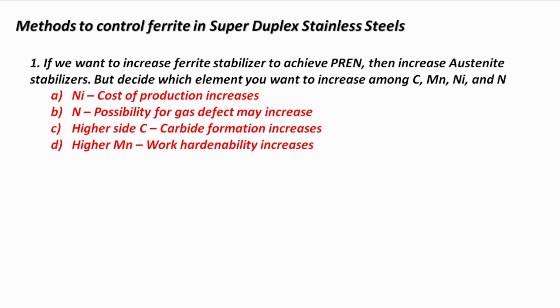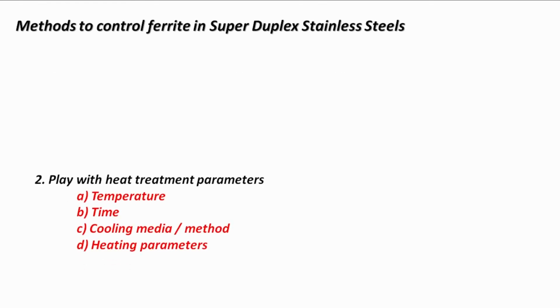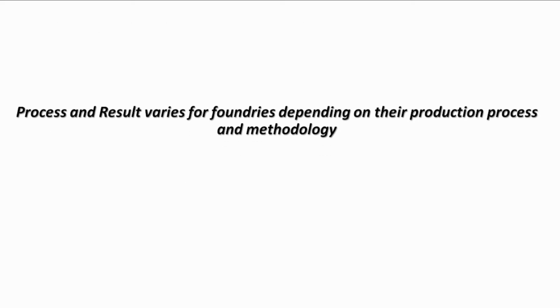These are the elements which you can see can help in increasing the austenite: nickel, nitrogen, carbon and manganese, and they also have their constraints in addition. The other parameter I can use is to control my heat treatment parameters by optimizing the temperature, time, cooling media and heating parameters. Process and results vary for foundries depending on their production process and methodology. So it is very important for us to understand our process, our methodology, and how we process the material, and to find the solution out of this.